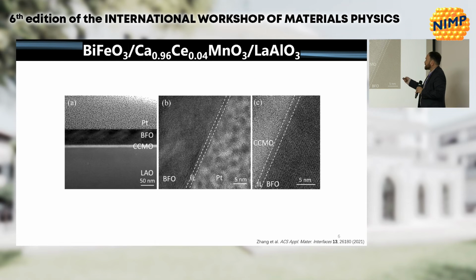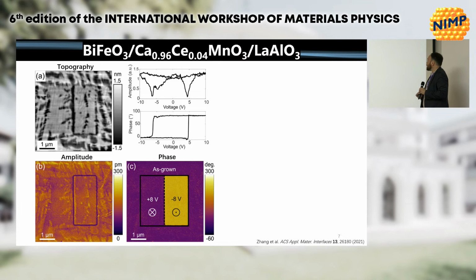Okay, so the film that we're looking at is bismuth ferrite. It's about 50 nanometers thick, and it has a nice interfacial layer, a dead layer at the surface. Here we show our height image after applying a switching bias of plus and minus 8 volts. So you can see in principle that the topography has changed. Here again is our PFM amplitude and our PFM phase. As grown, the film is already in a single domain state. Here's a representative switching loop, so a nice symmetric butterfly loop, a little bit of imprint, as you can see, and a switching voltage around 4 and minus 6 or minus 7 in this case.